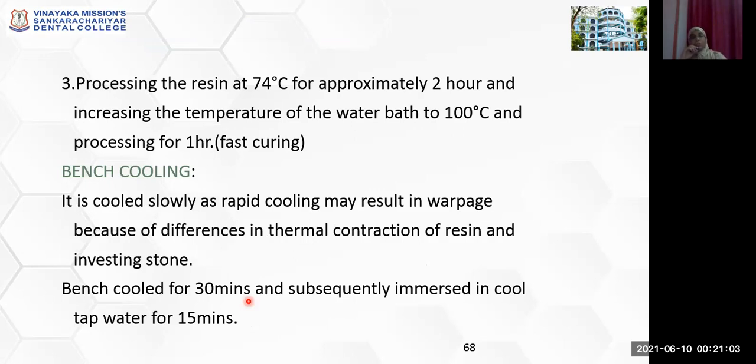Fine. Once you do that, you have to allow it bench cooling, because if you open it rapidly while it's hot, without bench cooling, there will be warpage, because so much stress inside is released all of a sudden. So you allow it to bench cool for around 30 minutes, followed by immersing it in tap water for around 15 minutes.